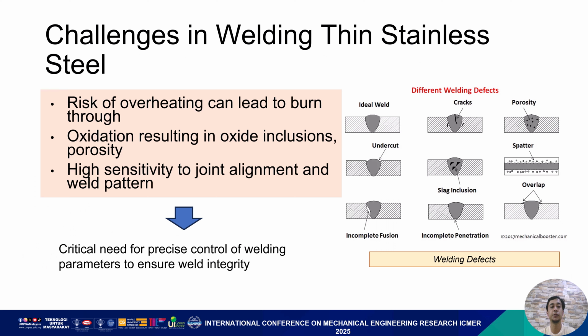What are the challenges in welding thin stainless steel? The first challenge is the risk of overheating, which can lead to burn through. Second, oxidation resulting in oxide inclusions and porosity. And last but not least, high sensitivity to joint alignment and weld pattern. All of these require a critical need for precise control of welding parameters to ensure weld integrity. As you can see in this figure, it shows a few types of welding defects that commonly happen in welding.